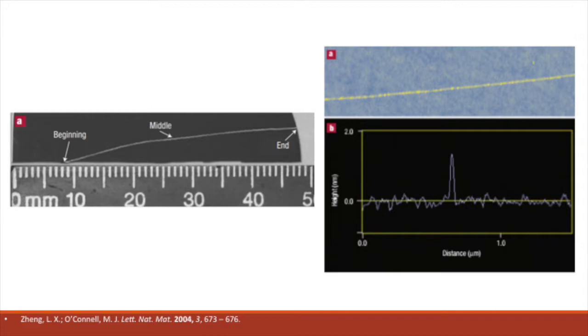A sample of a single-walled carbon nanotube can be seen in the figure to the left, where a ruler is held against an image of a nanotube created by superimposing 230 separate TEM images. The diameter of the nanotube was measured using atomic force microscopy, which is shown in the figure at the right. Here, the height represents the diameter, which is 1.4 nanometers.